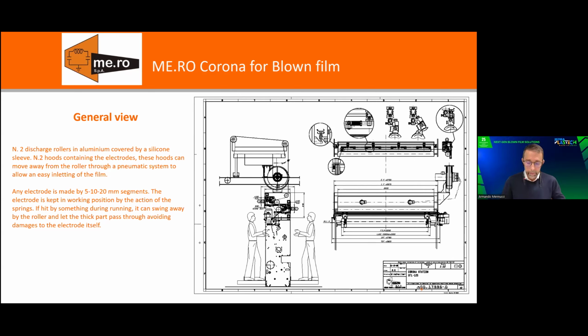We use segmented electrodes because most of the times on the blown film lines you need to avoid the treatment in some special areas of the web. So you need a segmented electrode. Going a little bit more in detail, I described the most important features that characterize our corona station for blown film line.